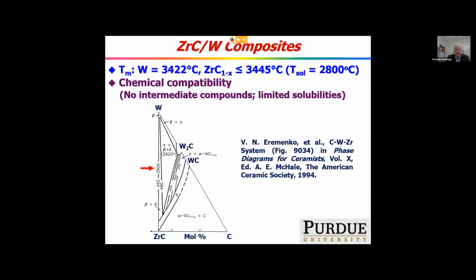Well, we focused on a cermet, and a particular one that has combinations of properties we think are particularly well suited for this application: tungsten and zirconium carbide. Tungsten is the highest melting metal. Zirconium carbide is also quite high melting. And when you put them together, the solidus temperature, that is the onset of melting, is still quite high, 2,800 centigrade. If you look at the tungsten-zirconium carbide-carbon phase diagram shown there, you can see the arrow pointing to the solidus temperature of 2,800 C.